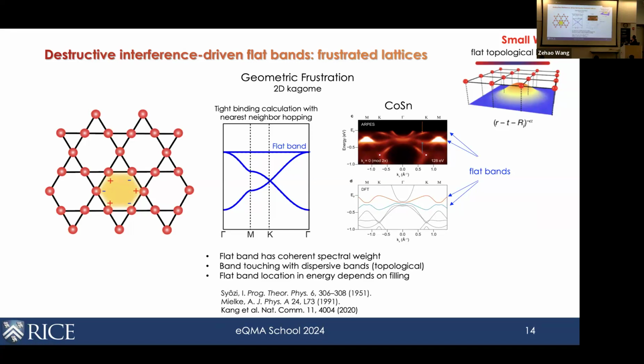And so in real materials, of course, this is a simplified scheme of what you would see for a Kagome system. In a real material, of course, you have the interaction with the other lattice sites, and this is maybe one of the best known Kagome systems, CoSn, where this is the DFT calculation for the bands that derive from this Kagome flat band, and then this is the photoemission data showing you a really good, reasonable match between the two.